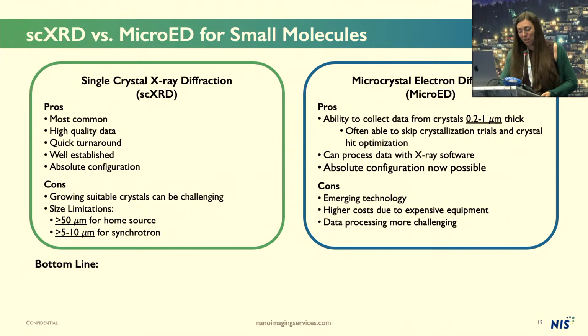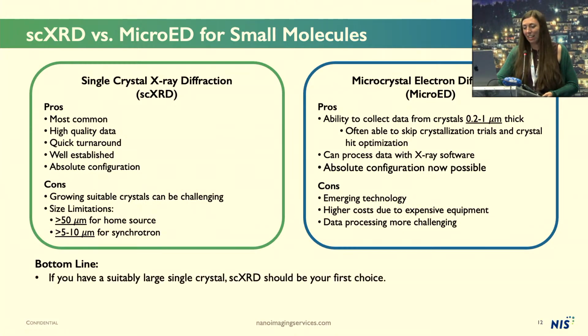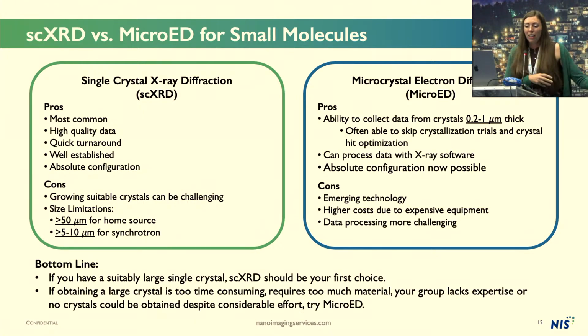So my bottom line opinion here is that if you have suitably large single crystals, just go ahead and do X-ray if you have access. I think that's probably the best first choice. But if obtaining a large single crystal is too time-consuming, requires too much material, maybe your group lacks expertise in growing crystals, or you just couldn't get one after a significant amount of time, I think that's where microED is there to help and still get structures.